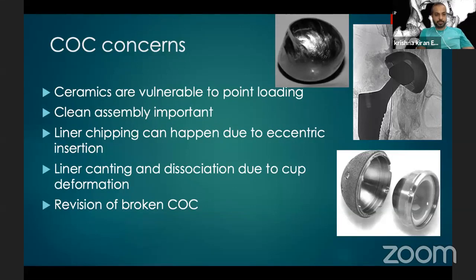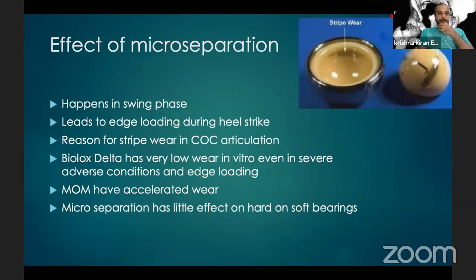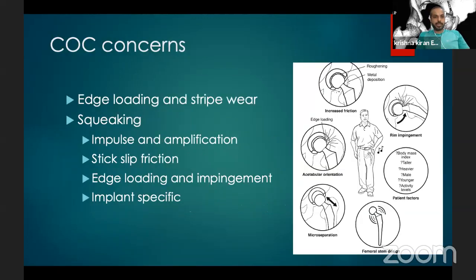Revision can be a concern with ceramic on ceramic, because the ideal revision would be to another ceramic on ceramic. If you put in a metal on polyethylene and ceramic debris is left inside the synovium, it will eat away at the metal head. The effects of microseparation, as I told you, must be considered. It has no effect on hard on soft bearings, but it has effects on hard bearings. If you have microseparation where the head comes out and hits the edge of the cup, there will be what is called stripe wear of the ceramic, and this can be noise producing.